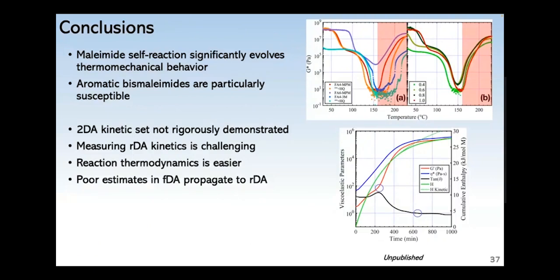So with that, I'll conclude this. I hope I've convinced you that the self-reaction for maleimides can significantly change the behavior of many DA materials. And we found that this aromatic bismaleimide that's so commonly used is particularly susceptible to producing irreversible changes in similar systems.